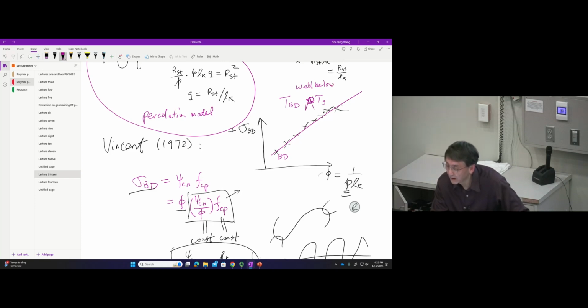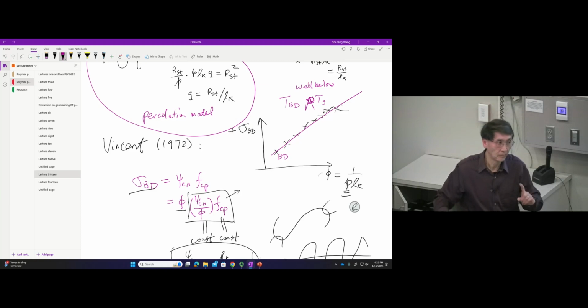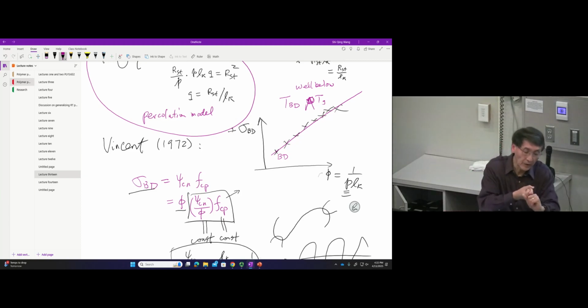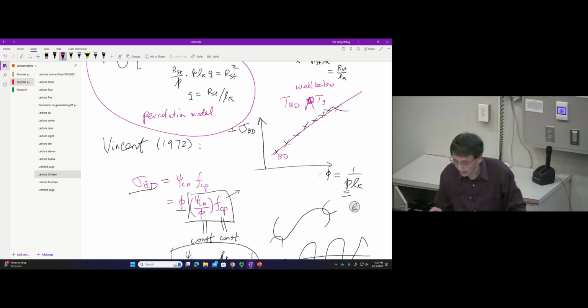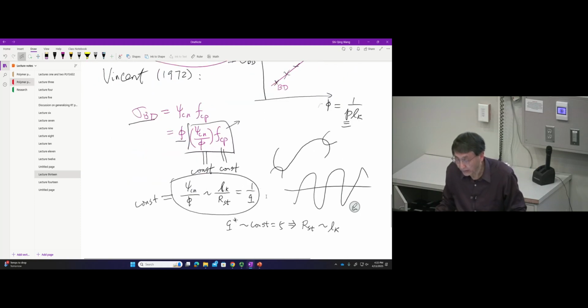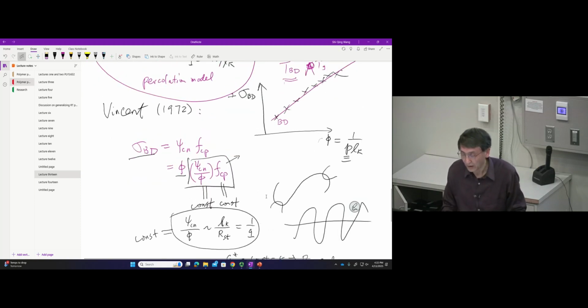So you can imagine the chains are all deeply embedded in this glassy state, to the point that how much force it takes to pull them out is no longer dependent on what temperature you're doing it at. Well, it's done at the BDT temperature. And basically, we have a result that's probably too good to be true: we don't anticipate this pull-out force to be constant, but by looking at the agreement between this expression and the experiment, we are deducing that it's a constant.